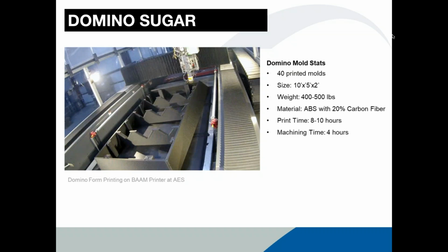The typical size was about 10 feet long, 5 feet wide, 2 feet tall, and they range anywhere from 400 to 500 pounds each. Now, the material of choice that we've been using, and what Oak Ridge learned early on doing some preliminary work with GATE and PCI, was an ABS plastic with 20% carbon fiber, which yielded a good strength and a good surface finish to cast on.